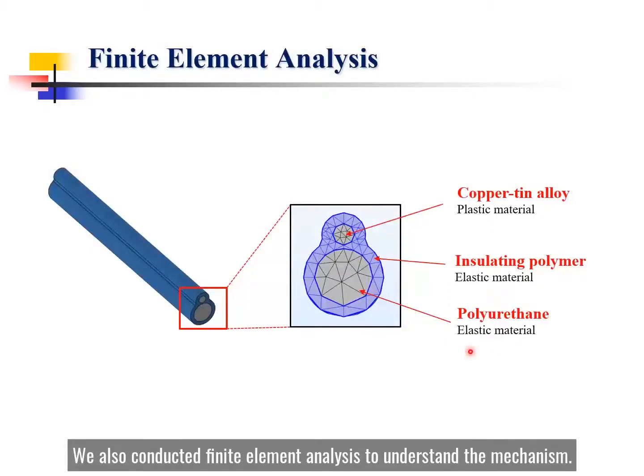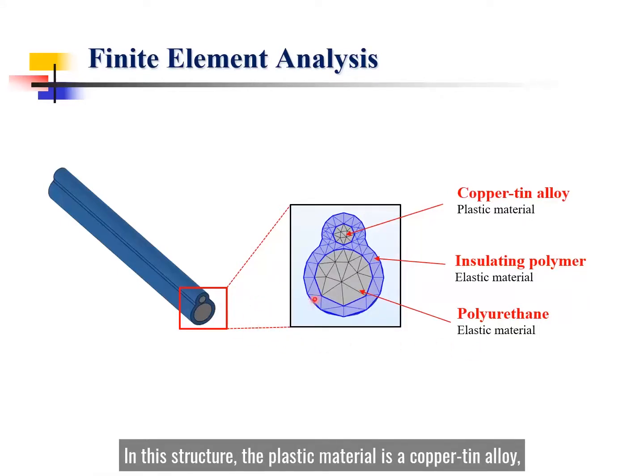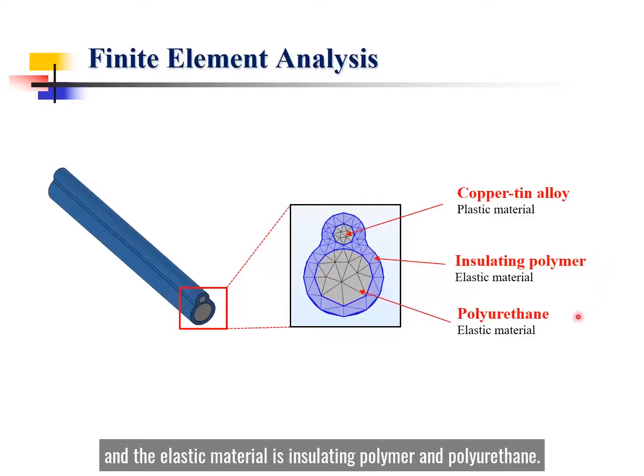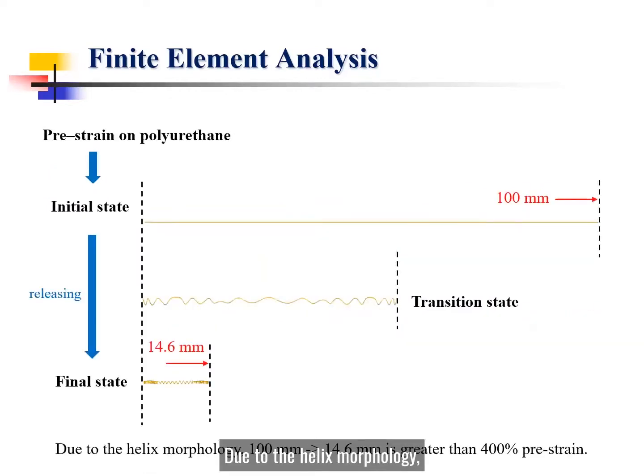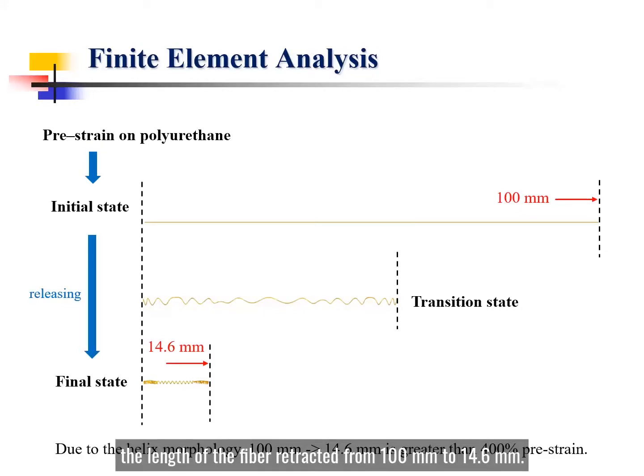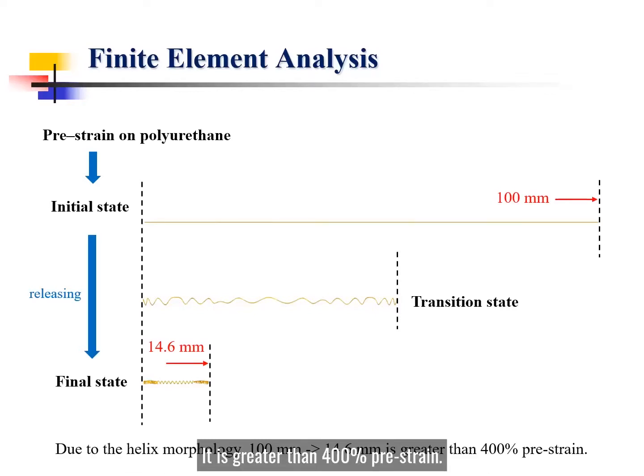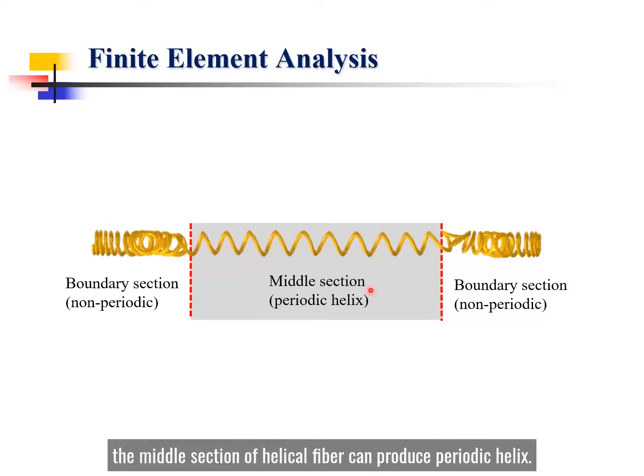We also conduct finite element analysis to understand the mechanism. In this structure, the plastic material is a copper-tin alloy, and the elastic material is insulating polymer, polyurethane. Due to the helix morphology, the length of the fiber retracted from 100 mm to 14.6 mm. It is greater than 400% pre-strain. And then we can see that the middle section of the helical fiber produces a periodic helix.